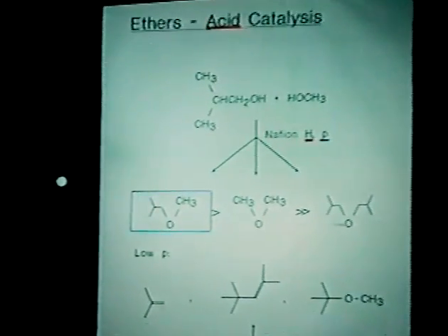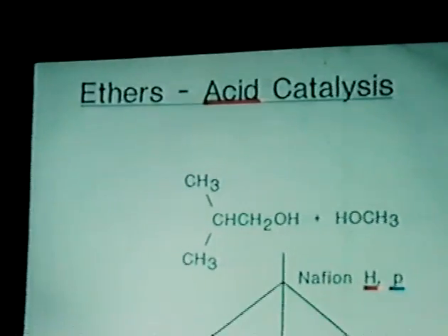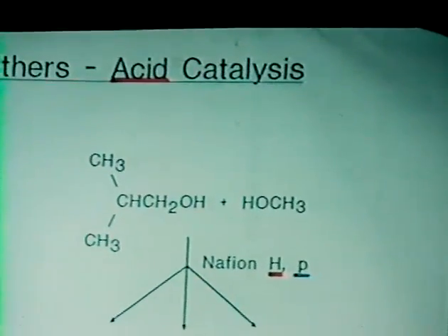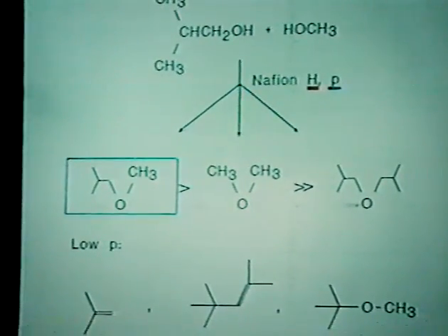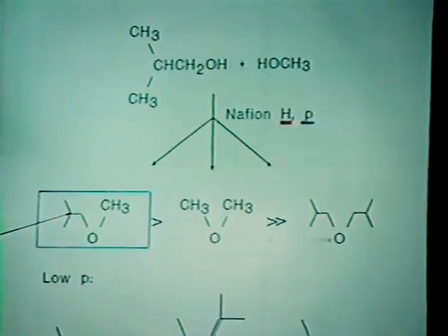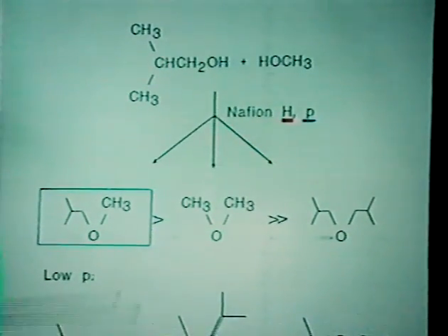What kind of principle did we use in the ethers? Both the chemical superacid principle as well as some physical chemistry, rather elemental, in which we determine that one alcohol is bonded more strongly than the other, and that is a key to the selectivity to the higher alcohol. But the product composition taught us also that some commonly anticipated reaction, namely carbonium ion, doesn't go here. There are some other reactions which I don't want to discuss now.